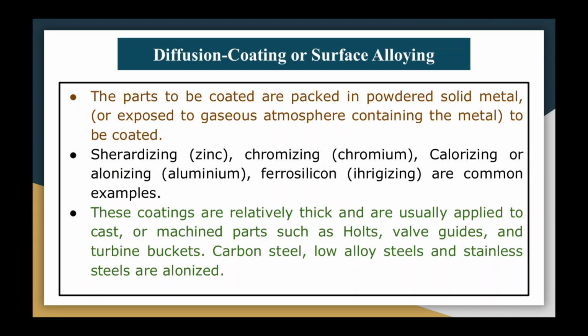calorizing, that is aluminizing, then ferrosilicon are common examples of this diffusion coating, and these coatings are relatively thick and are usually applied to cast or machined parts such as bolts, valve guides and turbine buckets. Carbon steel, low alloy steels and stainless steels are the aluminized products, and here a protective layer of aluminum oxide is formed on the iron or aluminum alloyed surface.